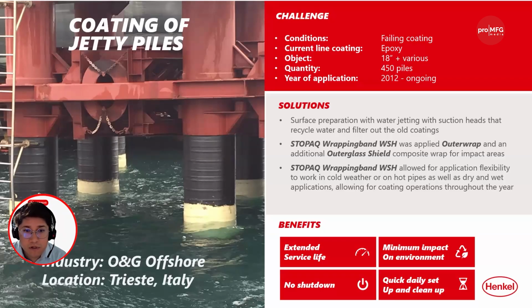So we came in with our Stopaq wrapping band solution, which can be applied in moisture and underwater conditions. So that allows us to be very flexible in terms of the application. We did 450 piles since 2012, and we are still doing them year to year. So what we are doing is not only extending the service lifetime, but also having minimum impact on the environment, because we don't need to do surface blasting. We do jet water blasting, and it allows us also to do it live. No shutdown needed, and we can adapt quite drastically with divers, with boats, and different flexible application methods.